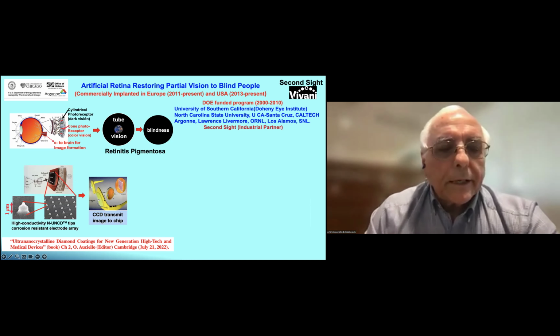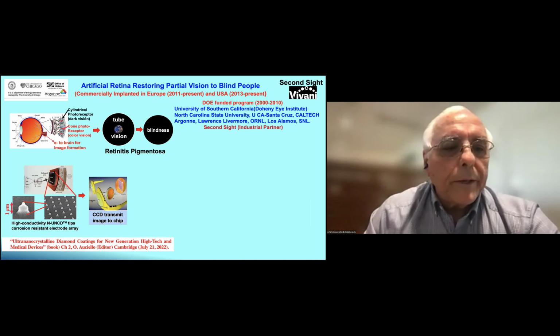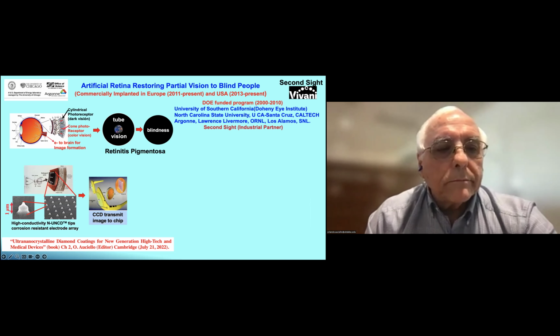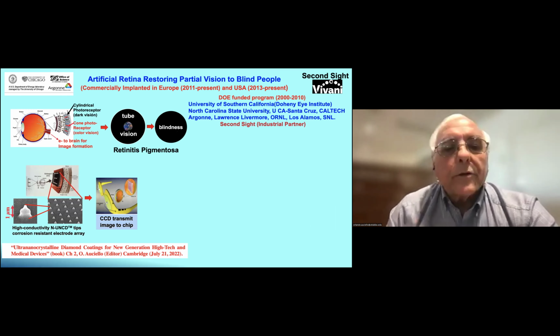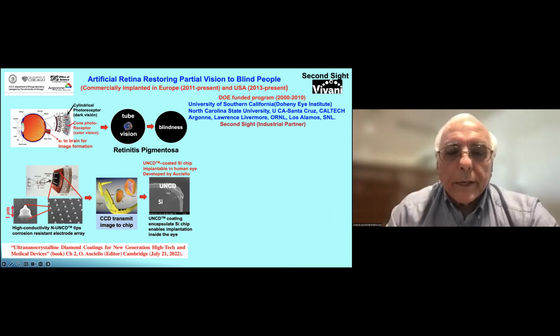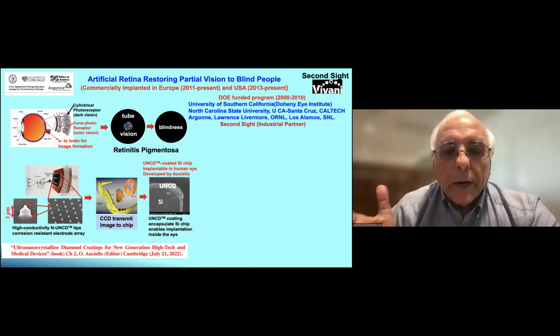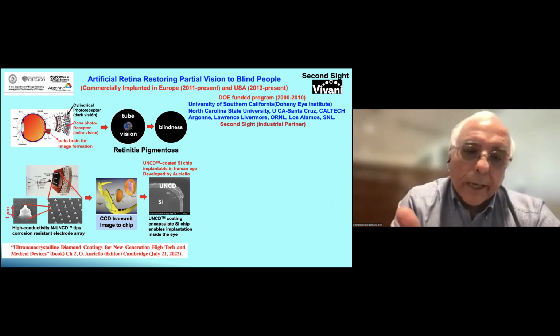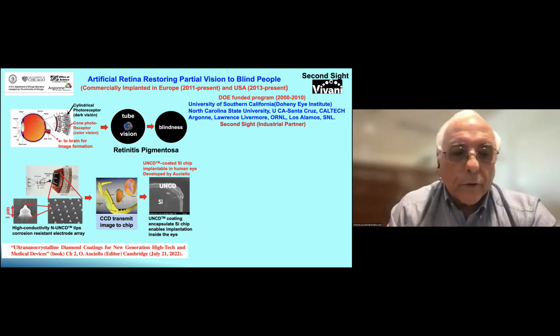The problem is that when Second Sight and the other people started putting silicon chips in rabbit eyes, they were destroyed in about 10 minutes. So I was giving a talk showing that our UNCD coating cannot be chemically attacked by any fluid. They brought me into the program, and I developed the UNCD coating to encapsulate the silicon chip. And we are the only ones that can do it because you cannot heat a silicon chip above about 450, 500 degrees, and we can grow this film at 350 to 400 degrees.